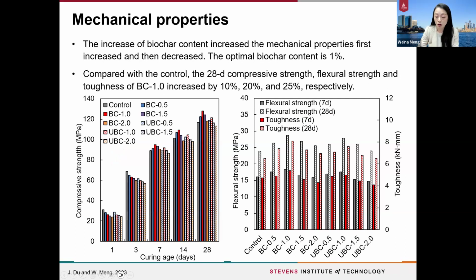And also here, one thing I want to note is that for most of the studies that utilize biochar in concrete, they saw significant drops in mechanical strengths if you directly use the biochar. But in our case, as we use this as an internal curing agent, with 1% the optimum dosage of the biochar, compared with the control, we have the 28-day compressive strength, flexural strength, and toughness increased by 10%, 20%, and 25% respectively.